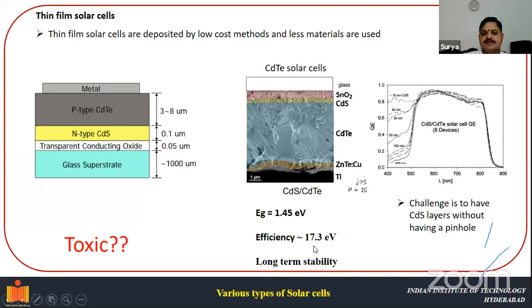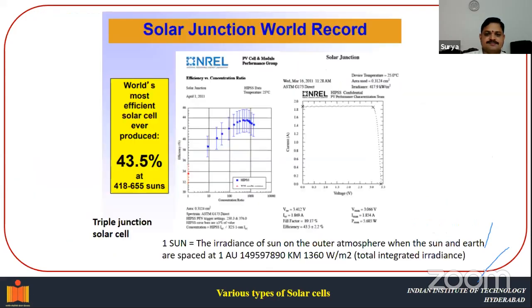Okay, so the kind of efficiencies that people have obtained using these cadmium sulfide or cadmium telluride based solar cells is of the order of 17.3 percent. And then the challenge is to have the cadmium sulfide layers without having pinholes. These layers are prone to have pinholes. The entire solar cell efficiency will depend upon how smooth or continuous your film is. For instance, if I have pinholes in the film, you cannot get the best efficiency from the solar cell. And on top of that, these materials are also toxic. Hence, we have to have different alternatives to convert the sunlight into electricity.